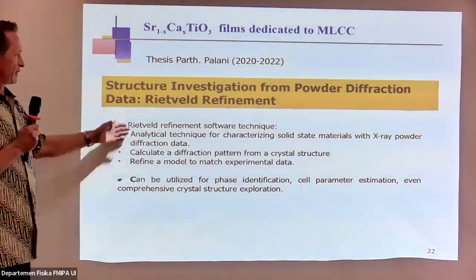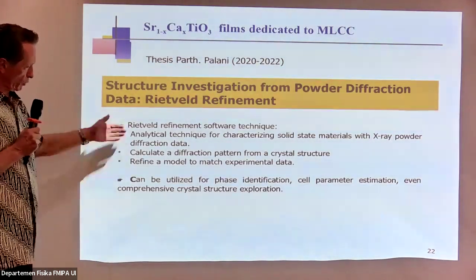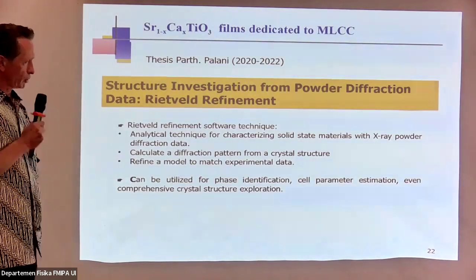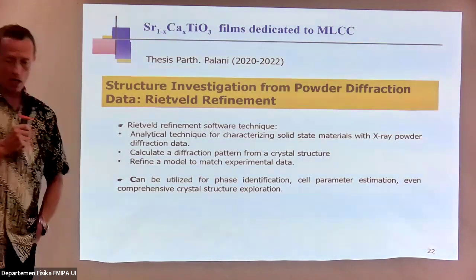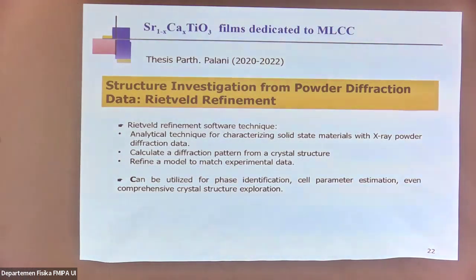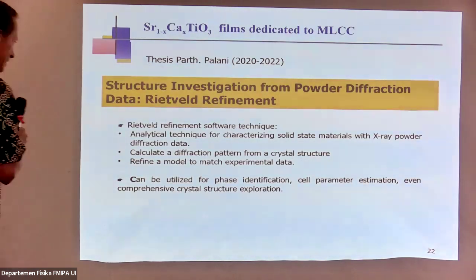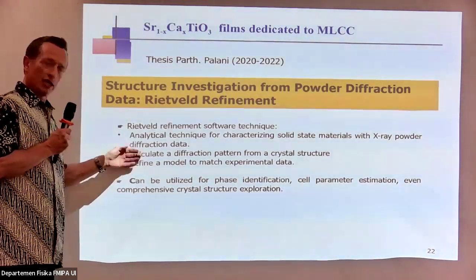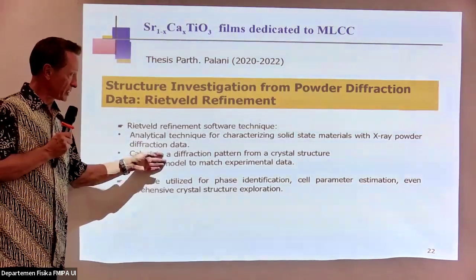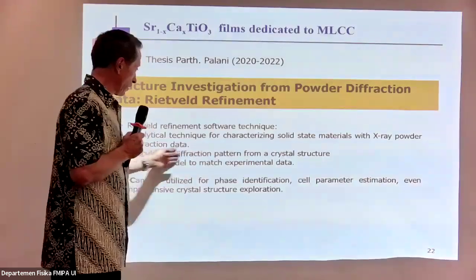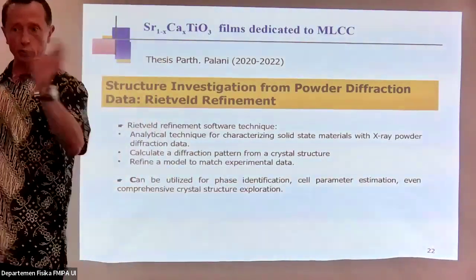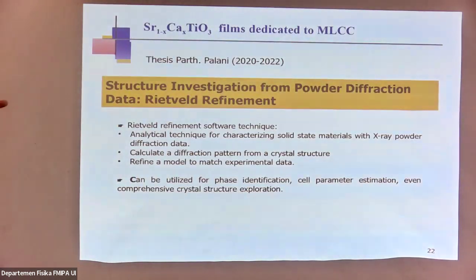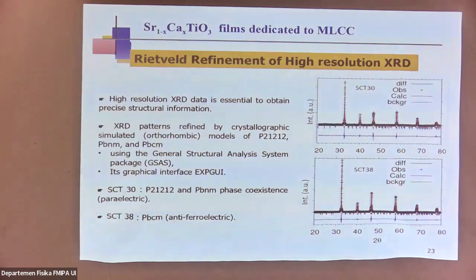So with this refinement, it's really interesting because you will make a full characterization of the solid state material, starting from the diffraction, X-ray diffraction. And then by computation, it's possible to calculate the diffraction pattern from a crystal structure. So you can superpose the experimental diffraction to the theoretical diffraction, the computed model. So that's what we've done for effectively some material.